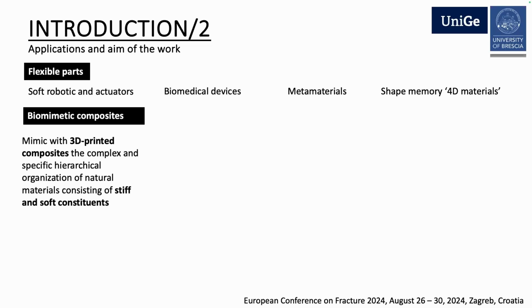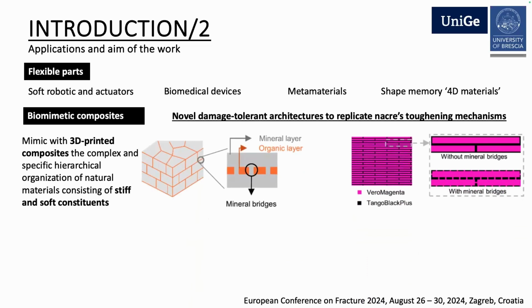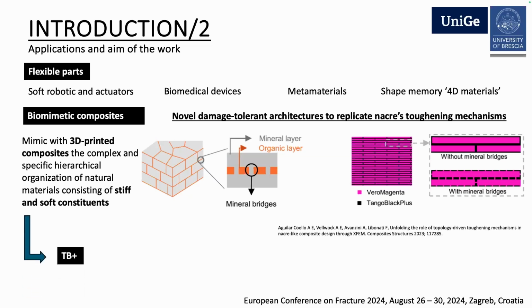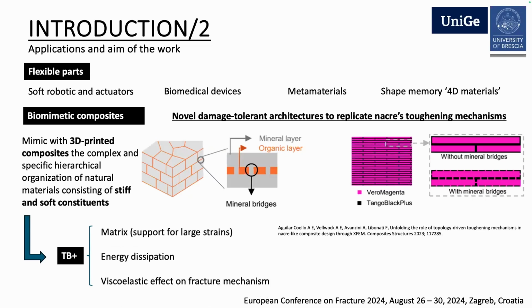stiff and soft constituents. And in our case, the context in which we developed this characterization of the Tango Black Plus is a previous investigation on the development of novel damage-tolerant architectures, which are inspired by the nacre toughening mechanism, where basically we have a mineral layer, which is embedded into an organic polymeric soft matrix. And in the 3D printed version of this composite, obviously the Tango Black Plus plays the role of the matrix, so it supports a rigid phase up to large strains, and it also helps in terms of energy dissipation and contributes to some fracture mechanisms.